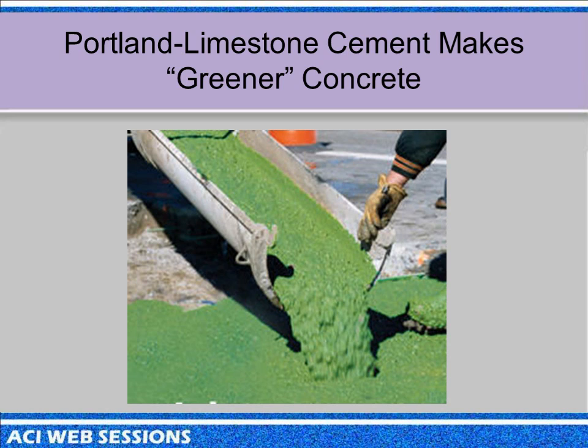But what we've also shown is, with increased limestone, there's an increased risk of thaumasite, but if you mitigate with the same amount of fly ash or slag you would normally use, you have exactly the same effect. You can prevent the thaumasite from forming. So we think we've got a solution to the potential problem.